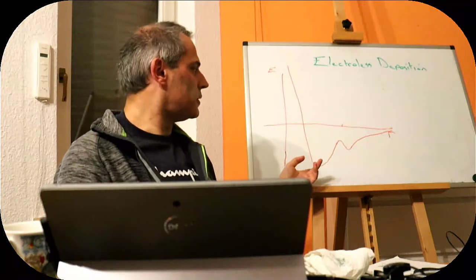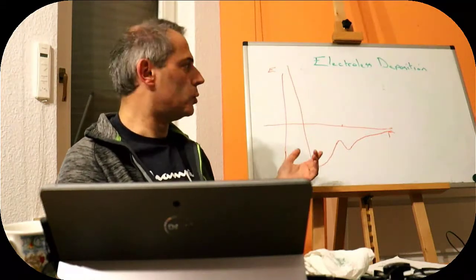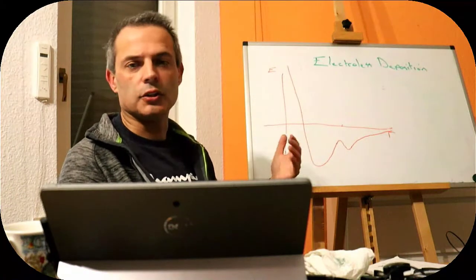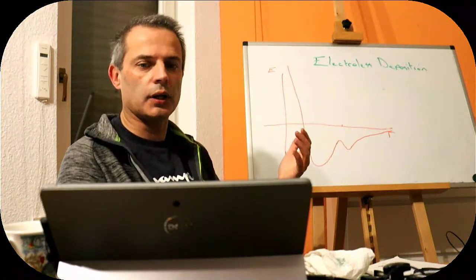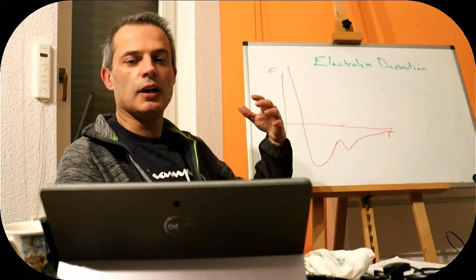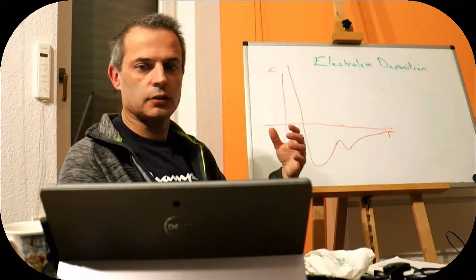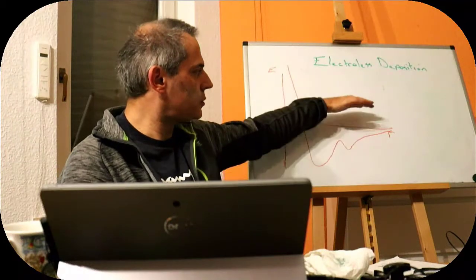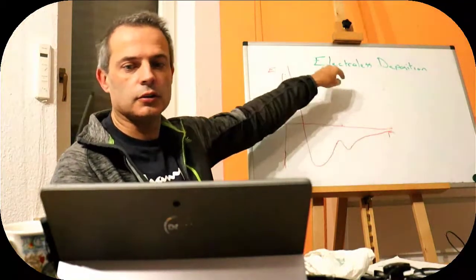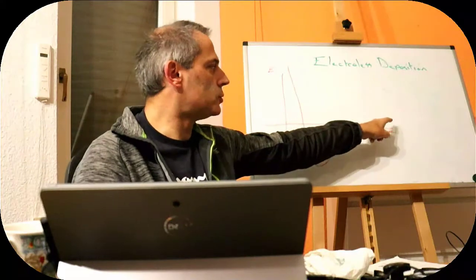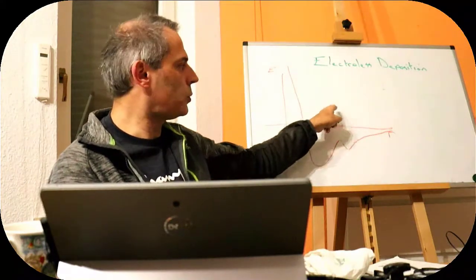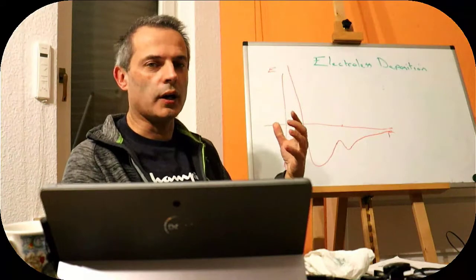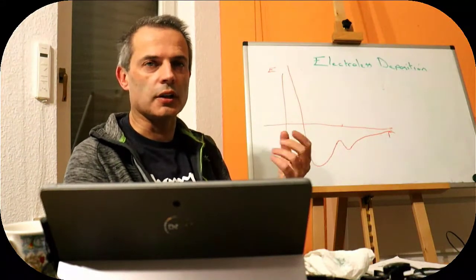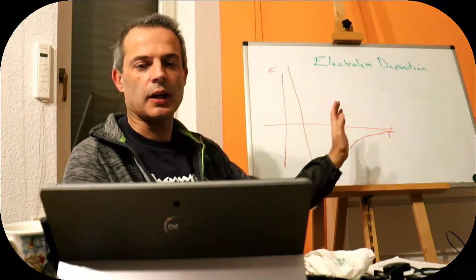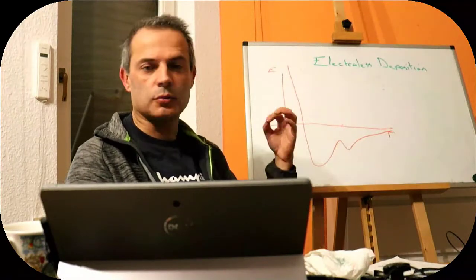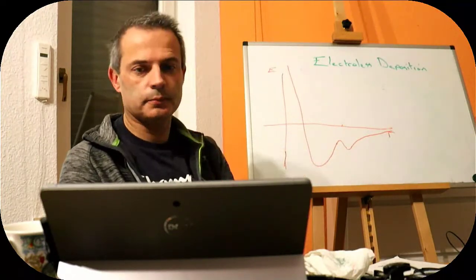When we push it any further closer, we're actually distorting the bonds in the material, and so that's obviously going to generate a repulsive force very, very quickly, and that's what this piece is. If we had like charged surfaces, all of this would be up here and it would decay down, because there's a repulsive electrostatic force, but we would still have a primary minimum where the atoms are interacting with each other, but they obviously would repel at most distances. Once we get close enough, however, they will stick.